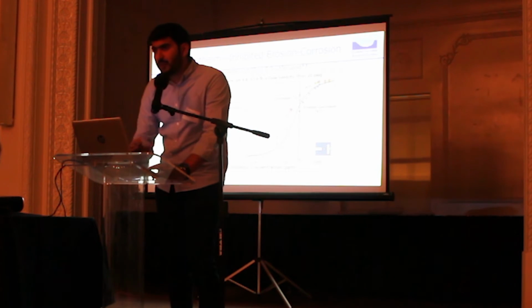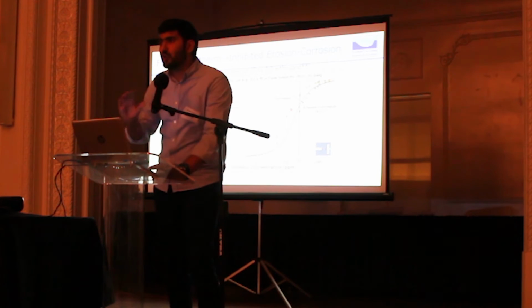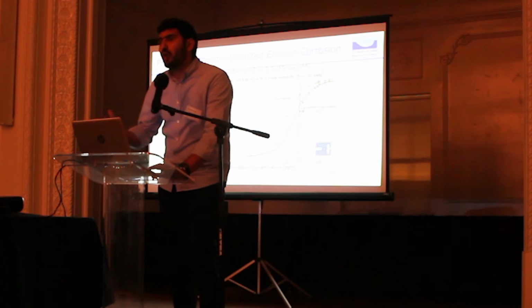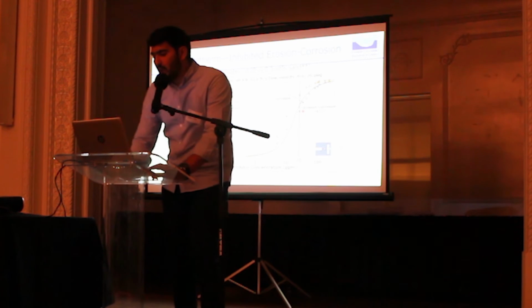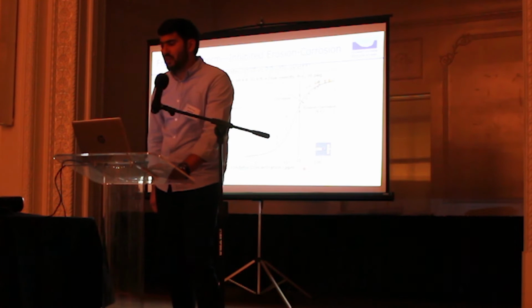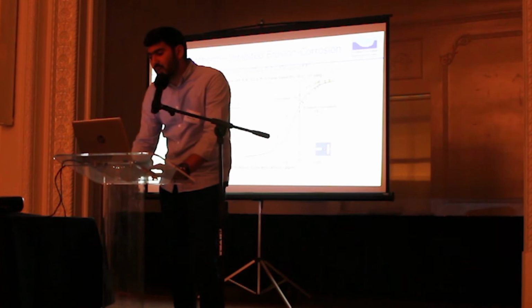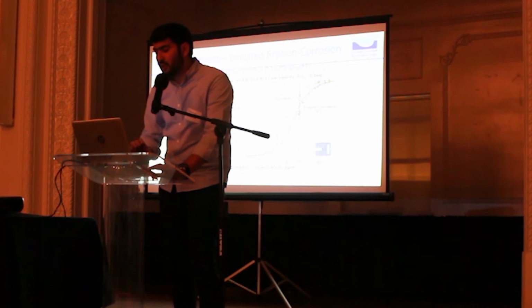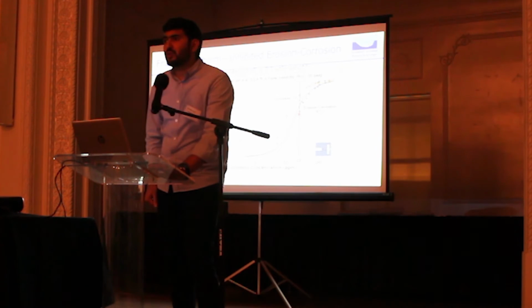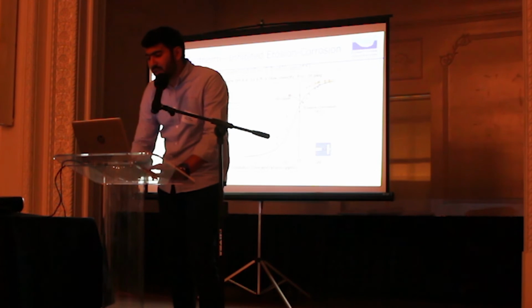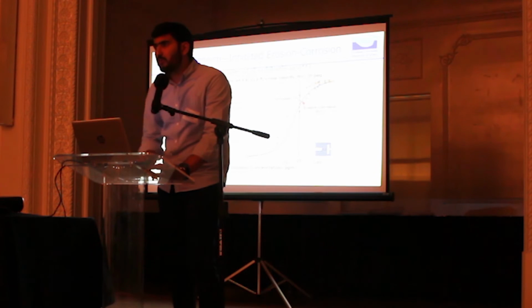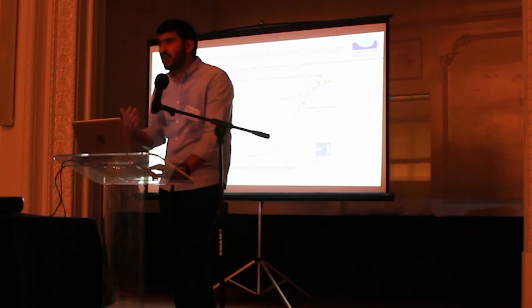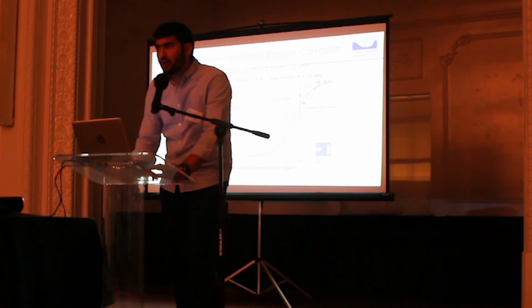As mentioned earlier, the green line represents the Frumkin isotherm fit to inhibited corrosion with no sand. The red line represents the Frumkin isotherm fit to inhibited erosion corrosion with 0.3% by weight sand concentration. Looking at the 25 ppm inhibitor concentration, the surface coverage by the inhibitor is higher in the absence of sand as compared to the surface coverage by the same amount of inhibitor in the presence of sand. Also, looking at this arrow here, there is a large shift to the right and downward by adding sand into the system. Therefore, adding sand into the system reduces the inhibitor effectiveness in reducing CO2 corrosion of carbon steel material.